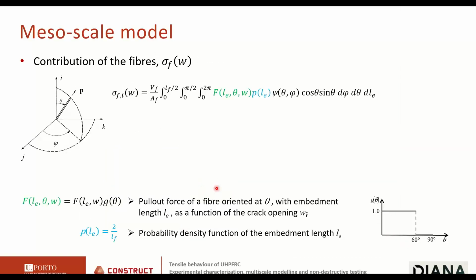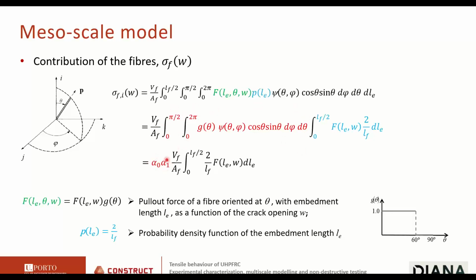So I will not go into too many details. If I want the contribution of the fibers, I have to integrate through all the possible fiber orientations, through all the possible fiber embedment lengths. To make this simple, here you see the pull-out force of a fiber oriented at an angle theta with an embedment length LE as a function of the crack width. We will consider that this is the product of a function that does not depend on the fiber orientation times the fiber efficiency function, which allows us to mathematically simplify the equation. The red part is only related to fiber orientation. It can be shown that the red part is the product of alpha 0 times alpha 1, the fiber orientation times the fiber efficiency factor.